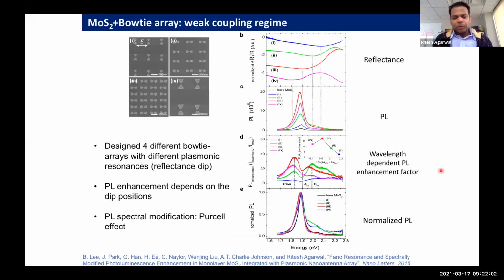We showed this, and by tuning the lattice modes, again via pure geometrical effects, we were able to tune the emission spectrum and also show blue emission, which means unthermalized emission from these two-dimensional materials. You can see this blue tail when the lattice mode is tuned to the high frequency side. That means the Purcell factor is pretty large, not as large as 1,000 because these are not the same structures as those curved geometries, but still large enough to compete to some extent with the thermalized emission.